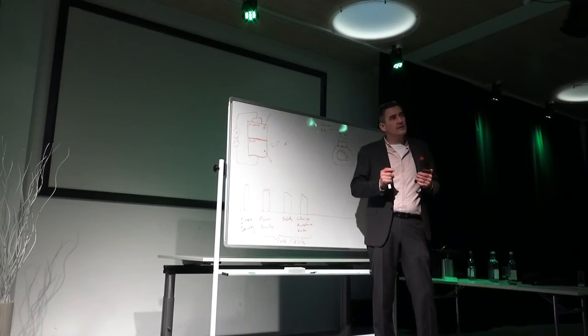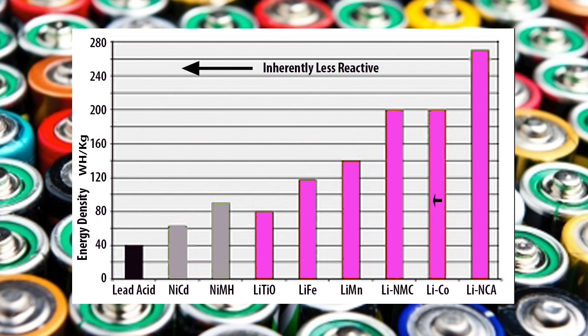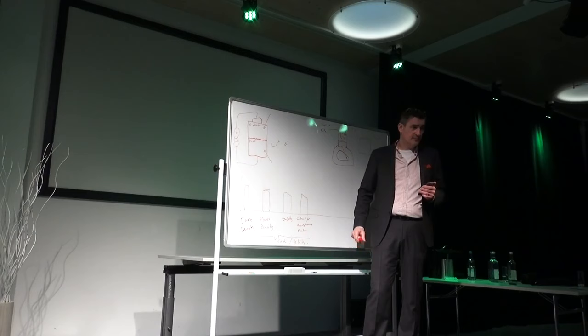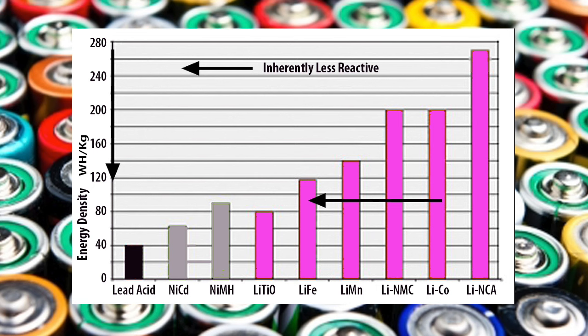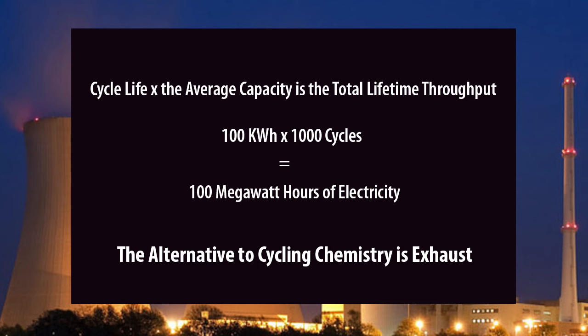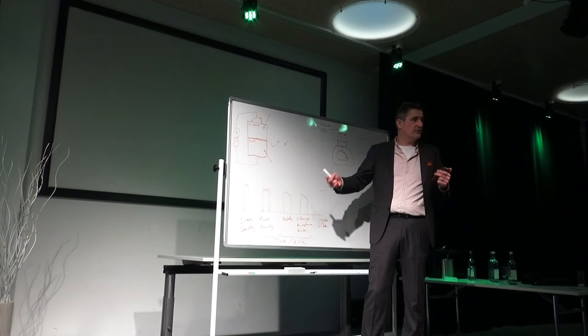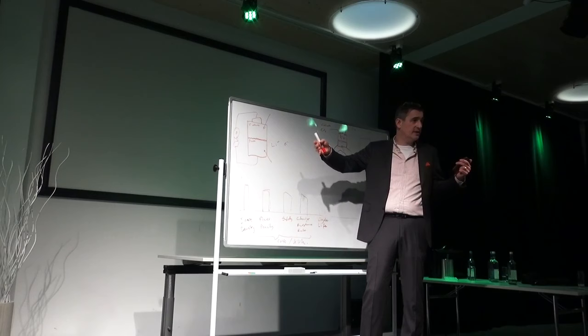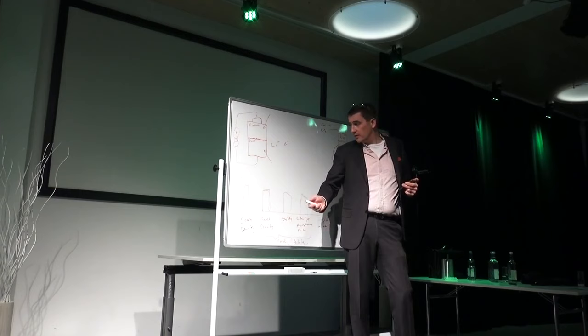One way of making a battery safer is to make the reactive materials less reactive — for example, instead of using a lithium cobalt oxide cathode, you'd use LiFePO4, lithium iron phosphate. But if you attack the reactivity of the material to increase safety, you immediately attack the energy density, which is why LiFePO4-type batteries are heavy. Cycle life is radically, radically important. Safety can also be dealt with at the pack level — with software, sophisticated electronics, structure, active cooling — mostly through isolation of one cell from others so you don't get a pack-level thermal runaway, while continuing to push up the energy density.